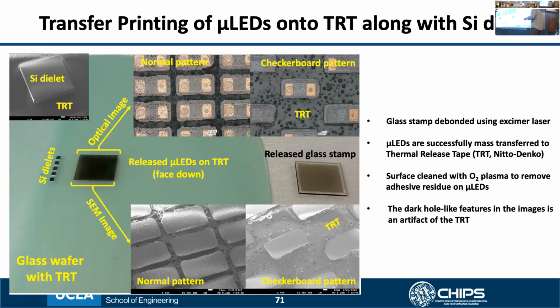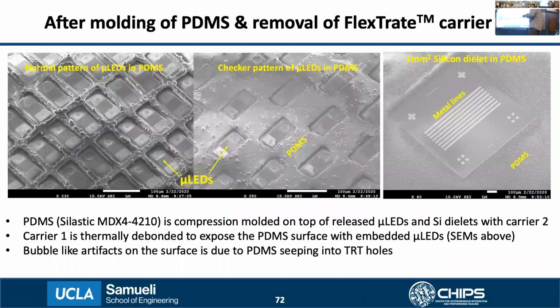So next we dispense the PDMS and compression mold the PDMS. And here you see some SEM images of the same sample after the first handler has been thermally debonded. So on the left side, you see the normal pattern of the LEDs which are embedded on the surface of the PDMS. The middle is the checker pattern, and the right side is a silicon dielet embedded within the PDMS.